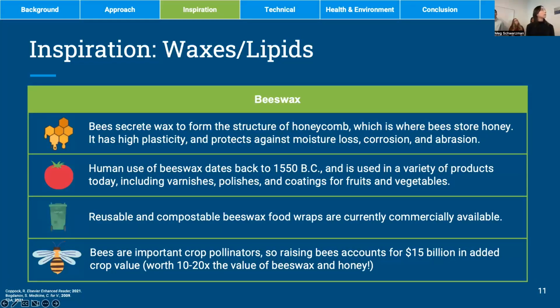So for our waxes and lipids category, we settled on beeswax as our most viable alternative. We did look at some other waxes. So we looked at paraffin wax, which we ruled out due to its derivation from petroleum. We also looked at carnauba wax, which is cheaper than beeswax, but has less ideal technical performance metrics. And there are also some concerns with the sourcing of carnauba wax, as it's been shown to be linked to deforestation and loss of biodiversity.